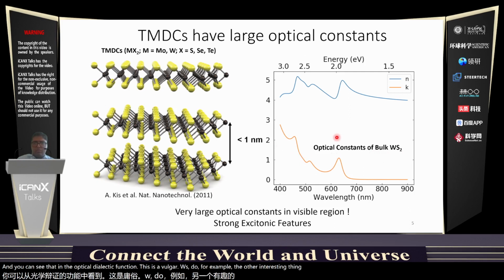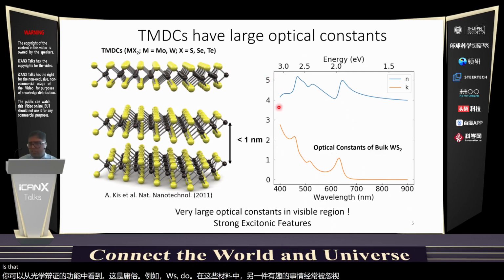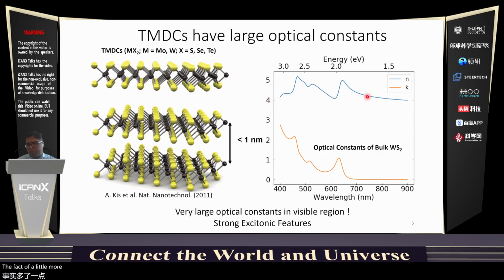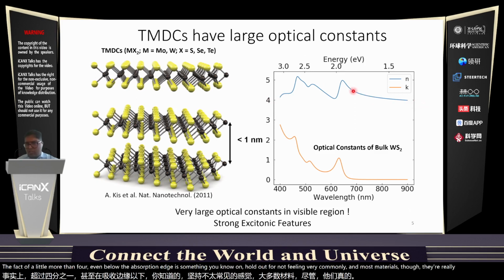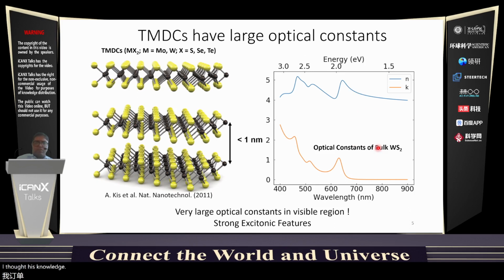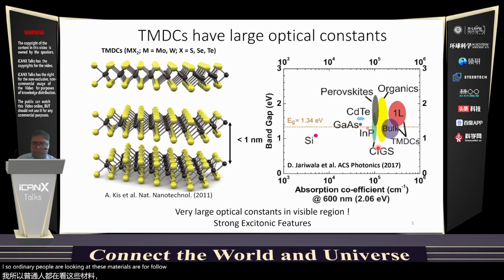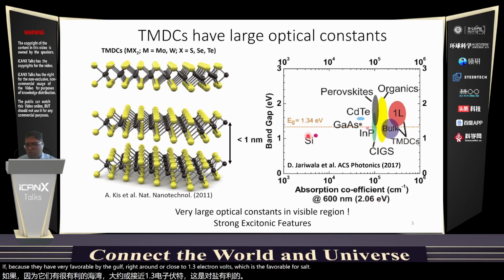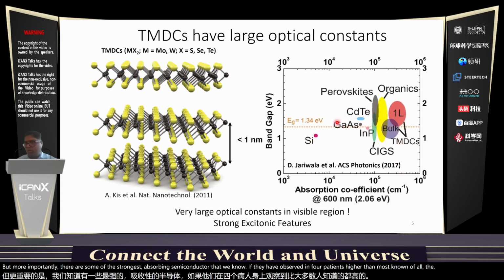The other interesting thing, which often gets overlooked in these materials, is the extremely high refractive index. A refractive index of more than 4, even below the absorption edge, is something not seen very commonly in most materials. So they are really materials with very high values of both the real and imaginary parts of the refractive index, or optical constants. Originally we were interested in looking at these materials for photovoltaic applications. One reason is that they have very favorable band gaps, close to 1.3 electron volts, which is favorable for solar energy harvesting. But more importantly, they are some of the strongest absorbing semiconductors that we know of. They have absorption coefficients higher than most known photovoltaic semiconductors, or most known semiconductors, period. So this was our motivation.